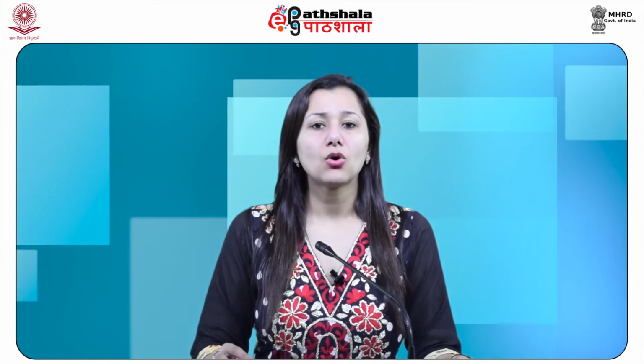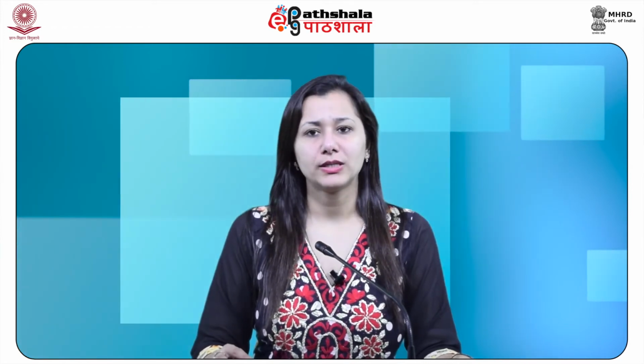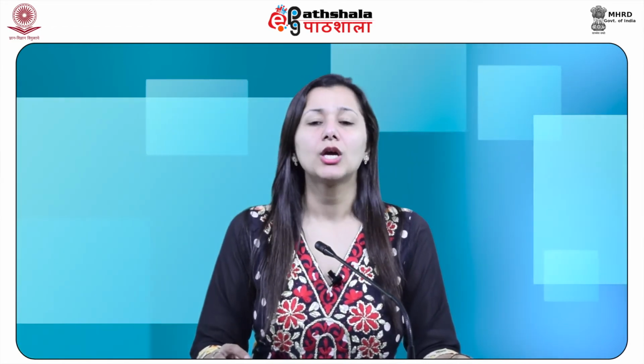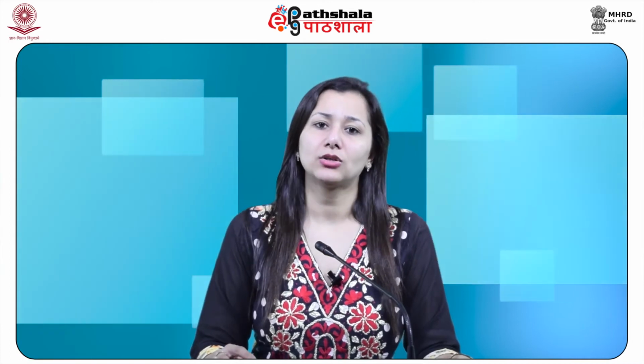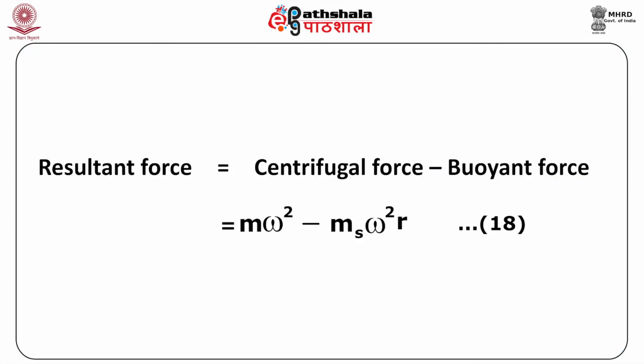The particle is also subjected to a buoyant force in addition to the centrifugal force, so that the resultant force acting on the particle is given by resultant force equals centrifugal force minus the buoyant force, which is further equal to m omega square r minus ms omega square r, as shown in equation 18, where ms is the mass of the displaced solvent.